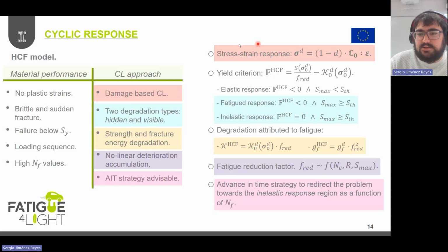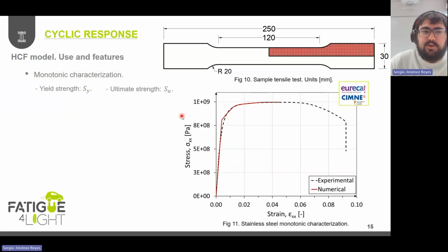So this basically describes the main characteristics of our constitutive law. And now let's see how this constitutive model is being used and some of the main features coming from it through some examples. So basically, in order to use this constitutive model, the first thing that we should do is characterize the monotonic response of the material. In this case, you can see the experimental results for a stainless steel metal and the corresponding calibration made from a numerical perspective.